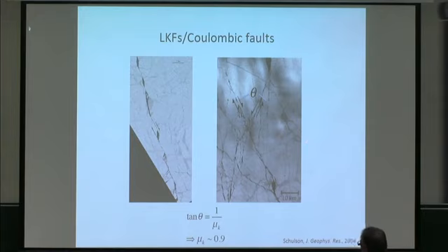If you look to the right, you see a set of intersecting linear kinematic features, and I call them Coulombic shear faults. The implication here is that these features are being created by a compressive, far-field, wind-originated compressive stress. And here they're intersecting, two intersecting type features. And from the theory of brittle compressive failure, what we're seeing, this pair of intersecting features can be described solely in terms of the coefficient of friction. These are conjugate faults, we interpret them to be.